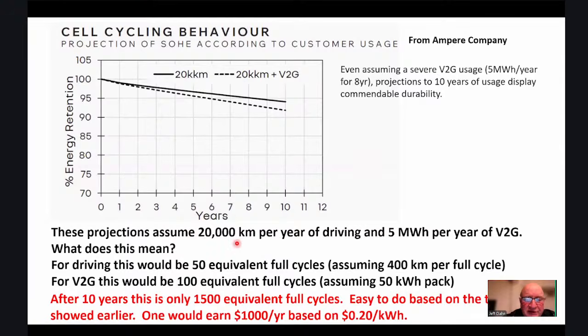Okay, so 20,000 kilometers of driving per year and 5 megawatt hours per year vehicle to grid. What does this mean? Well, for 20,000 kilometers of driving, that would be only 50 equivalent full cycles, assuming 400 kilometers per full cycle. If you were charging and discharging frequently, it would be more than 50 cycles. But when you add up the total energy stored and delivered, it's equivalent to 50 100% state of charge cycles.